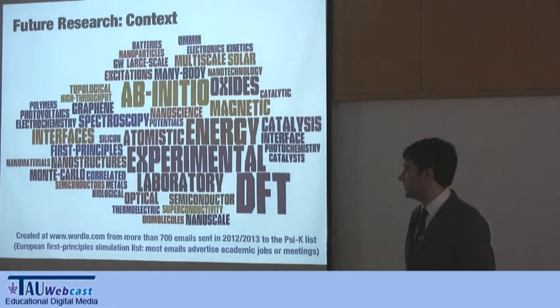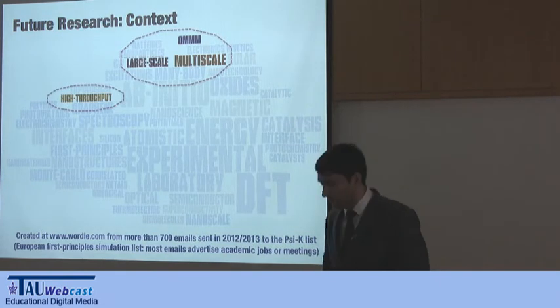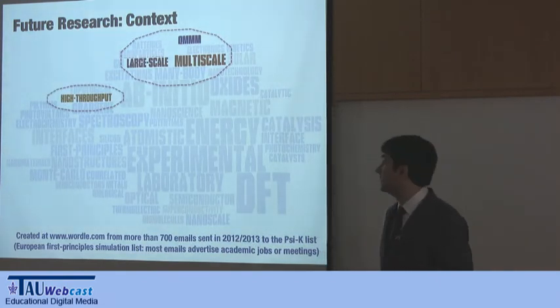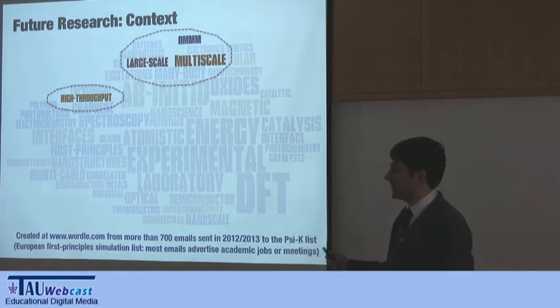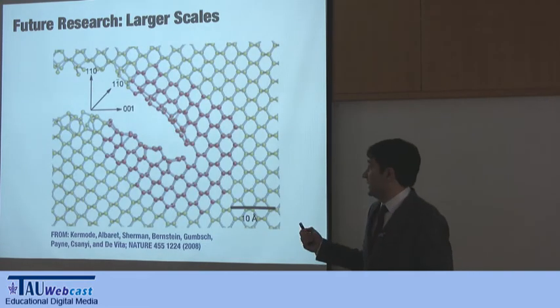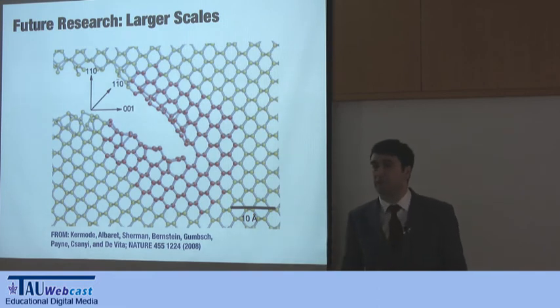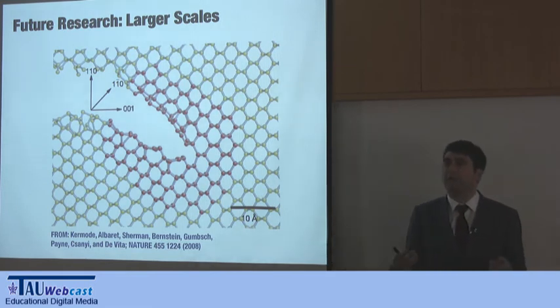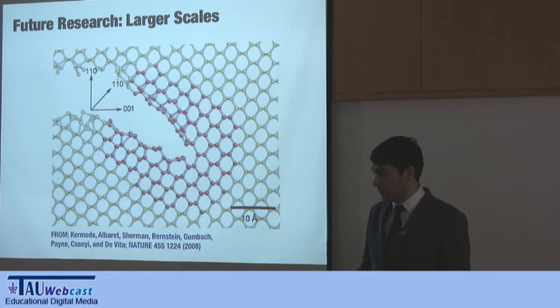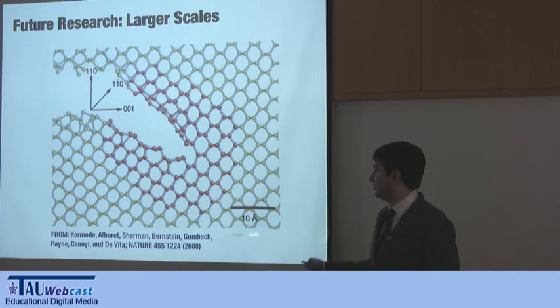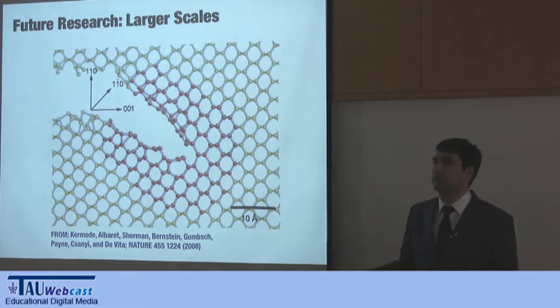Okay. So I showed this map before, and two of the research directions I want to go with are what they call high throughput methods and also larger scale methods. So, larger scales. This is an example I took from the group I was in at Cambridge, although I had left already. They were interested in studying the propagation of cracks in silicon. This is a problem that has a huge size for your simulation, because the crack will move along nanometers and nanometers of silicon. So you cannot even imagine doing it with only DFT.